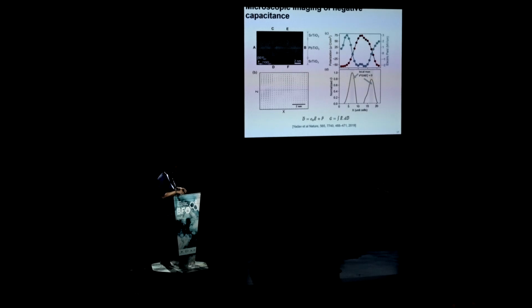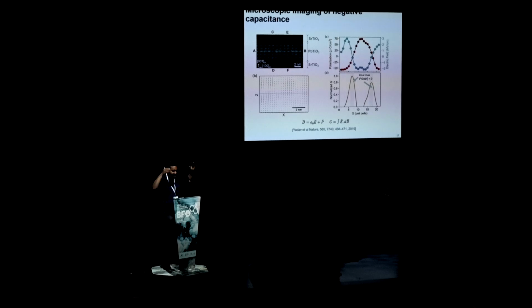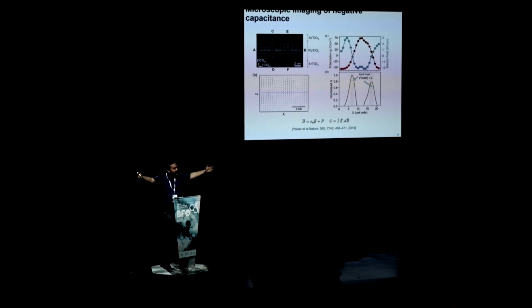Now, how that is connected to the energy landscape is also something we learned from this experiment, in the sense that we can look at the energy landscape locally. And locally, I will see peaks and troughs. The peaks are where the energy is stored and polarization is suppressed. It will look like a double-well-shaped energy landscape, but there are many of them locally stabilized, so it's not one. If you are looking at very pure physics, you'd say I want to define one energy landscape for the entire system. That is a very different thing. But if you are looking locally, you can still use the concept that I have a stored energy, so that the second derivative is becoming negative. That's how, at least, I think about this. Thank you.